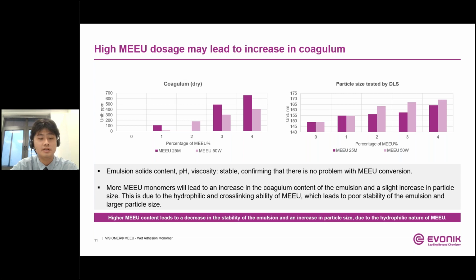However, when you see the figure on the left side, the coagulum content increased with the increase of MEEU monomer. The reason behind it is that MEEU is a hydrophilic monomer, which may easily cause particles to agglomerate once the dosage is very high. In the figure, it shows over 3%, the coagulum grows very rapidly. And if we look at the right-hand side chart, the increase of particle size may also be due to the thickening of the outer layer of the particle caused by those hydrophilic monomers. Therefore, due to the MEEU hydrophilicity, a high dosage can lead to instability in the emulsion. So we recommend lower than 3% as the low-risk dosage.